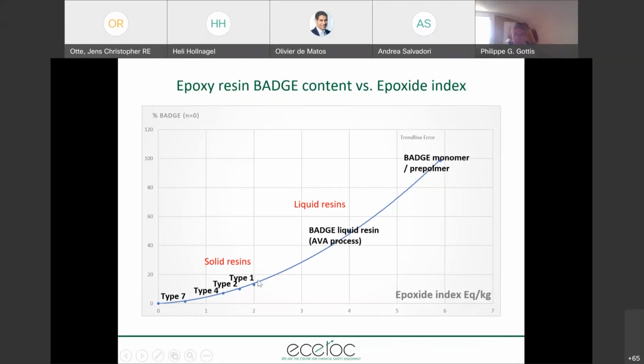So the solid resins are delivered as dust or flakes, and the different technical grades are named types. Type 1 is a solid resin with the lowest molecular weight here, and the highest ratio of epoxide groups. There are obviously at the end only two domains which are really of interest. This is BADGE substance, which is already registered, and the domain of the solid polymer resins, starting from type 1 upwards.